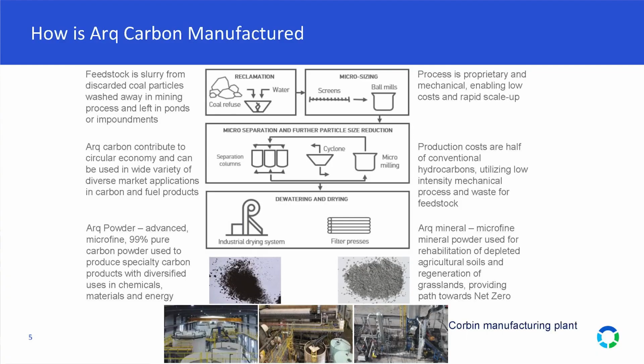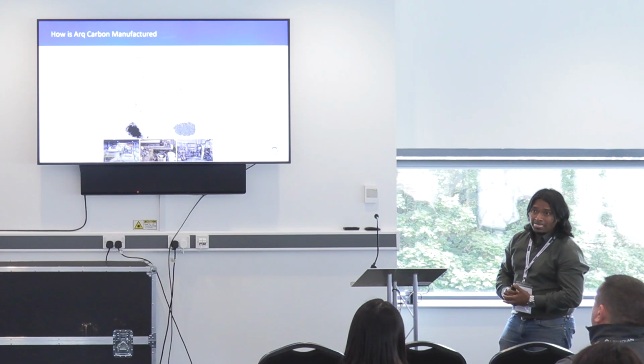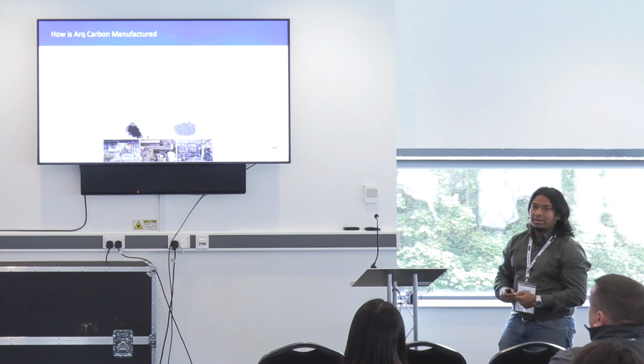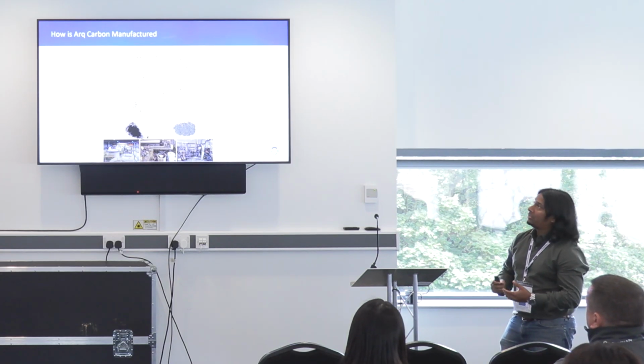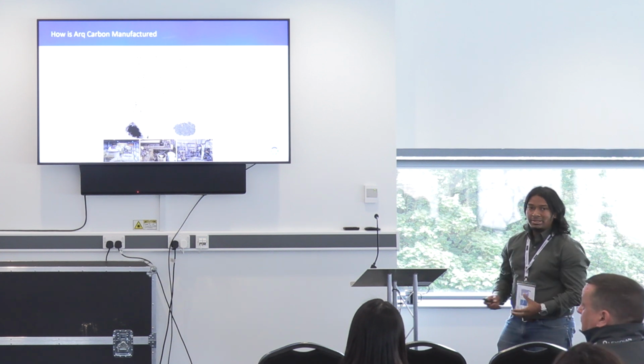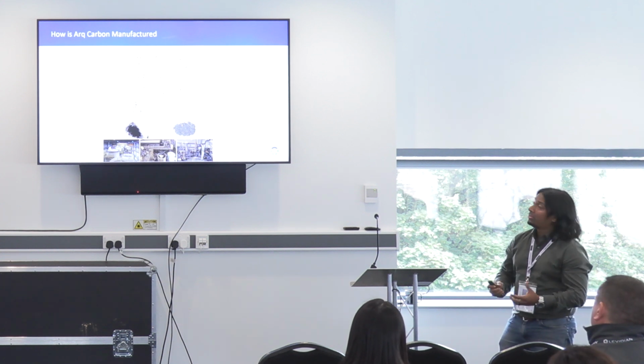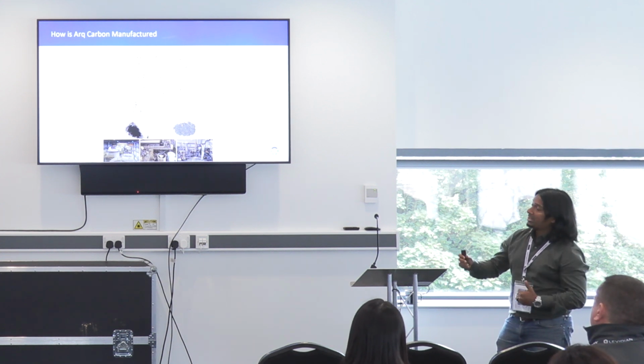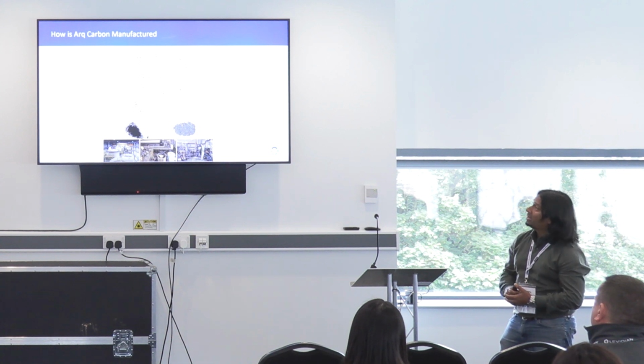So I won't really dwell on this too much, but it's just using existing technology that we've built up plant. So you see some images at the bottom that typically rely on froth flotation as well as milling in a very iterative manner. So the idea really is to break the coal fines down into much smaller particles, which in turn liberates the ash or the mineral entities, which gets floated and removed through hydrophilic, hydrophobic interactions.